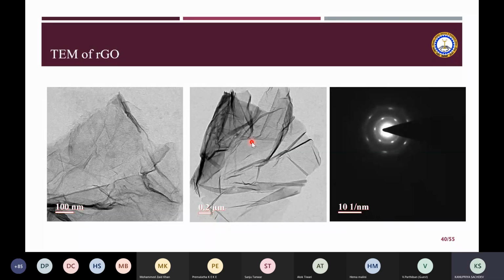This is the transmission electron microscope image of the reduced graphene oxide. We have just seen the scanning electron microscope pictures for this RGO, and this is the transmission electron microscope. You can see that again it's a wrinkled film, and it has very good transparency, but it is not uniform and smooth. And this gives you the polycrystalline nature.